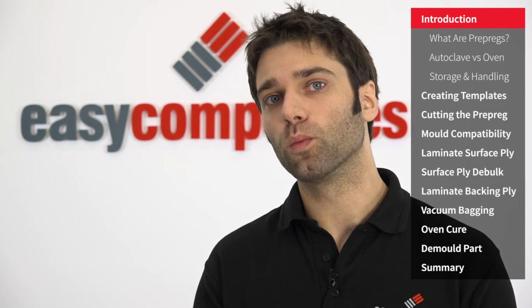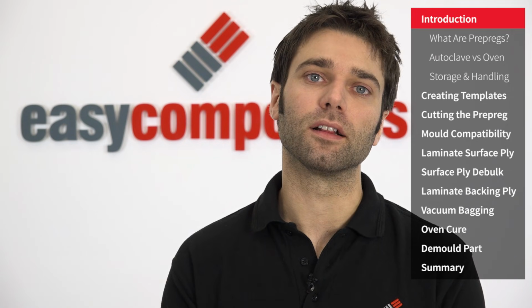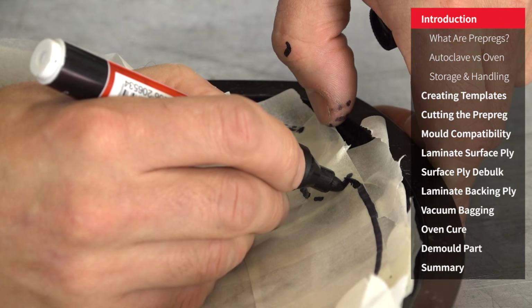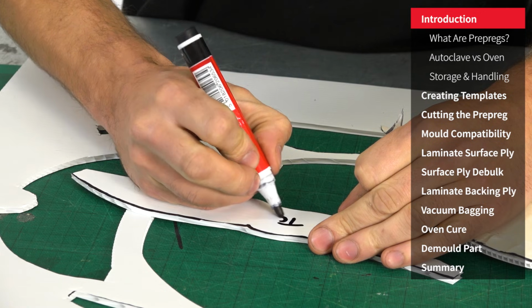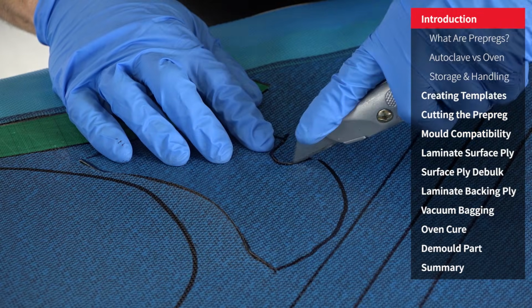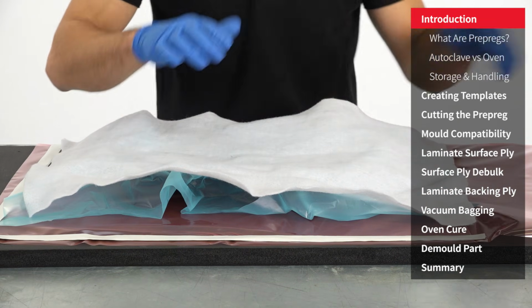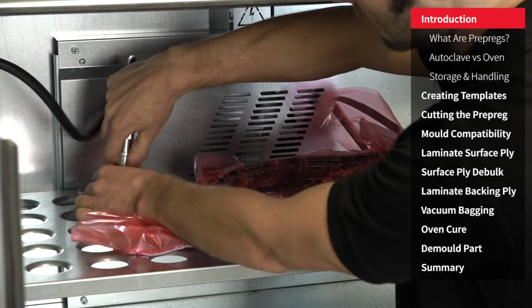I'll briefly explain what pre-pregs are, how they're shipped and handled, and the equipment that you'd need to process them. And then I'll demonstrate in more detail the process of templating out, cutting the pre-preg, laminating the surface and then the backing plies, and then the correct way to vacuum bag the component. Finally, we'll oven cure the component under vacuum.